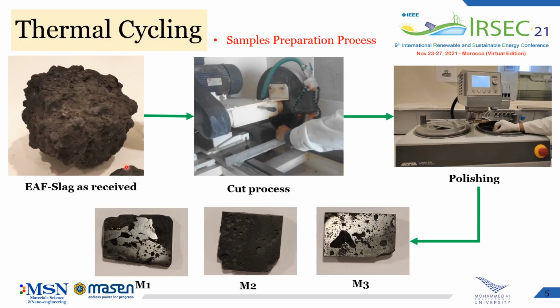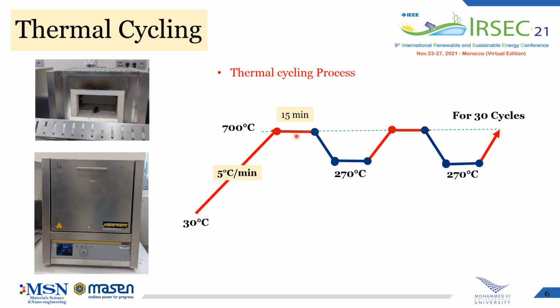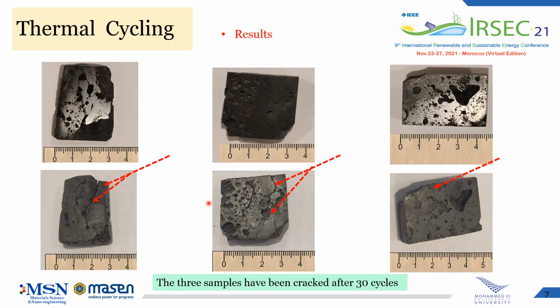I will start with thermal cycling of the received material, and thus to simulate the charge and discharge operation of thermal energy storage system. We have prepared 3 square samples and we have polished their surface to better visualize the state of surface before and after thermal cycling. The thermal cycling was done in laboratory furnace between 700 degrees C and 270 degrees C using a heating rate of 5 degrees C per minute for 30 cycles. After the 30 cycles, all the samples have been cracked as you can see in the picture.